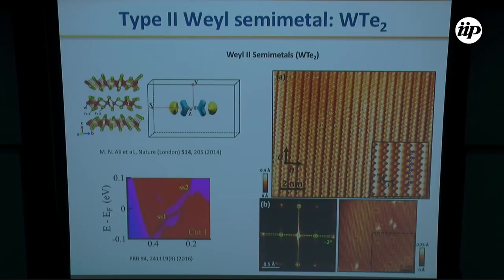In the top part, I show you the band structure for the bulk, and in the lower part, the band structure for the surface. In the bulk, calculations show that we should see two small hole pockets in blue and two small electron pockets in yellow. In the surface band structure, we observe these two Fermi arcs, one below the Fermi level and one above the Fermi level. The one below the Fermi level has already been observed by ARPES, but as we know, ARPES has no access to the empty states.